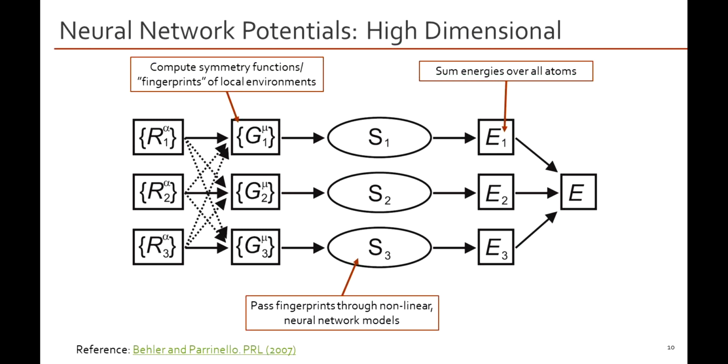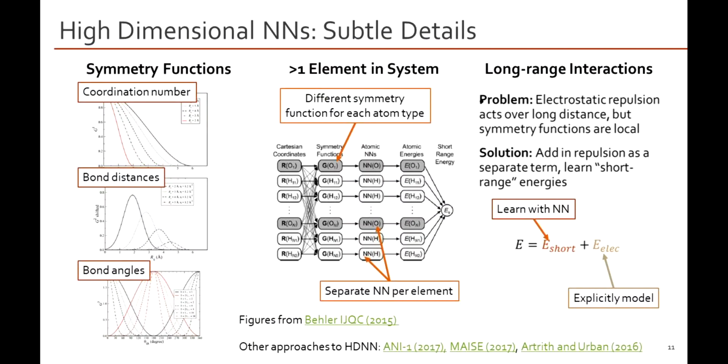to describe complex materials. Now, the first of which is I use a few different varieties of these symmetry functions to describe an atom's environment. I have some which give me a coordination number-like parameter, where I use a radial basis function like a Gaussian, which effectively counts up how many nearest neighbors this atom has. So those are one set of the fingerprints I use to describe.